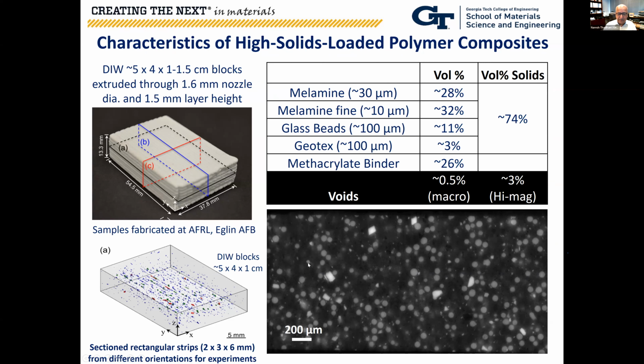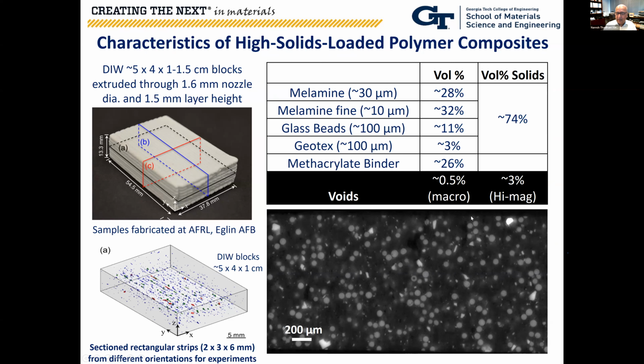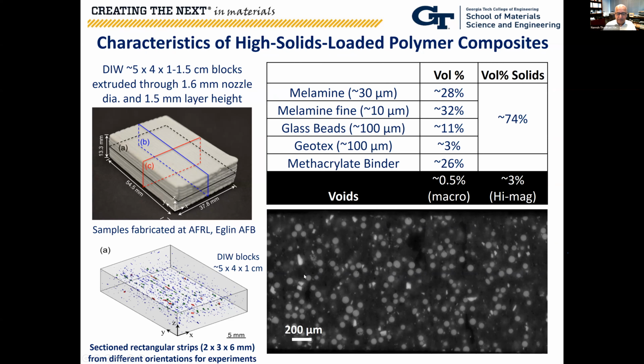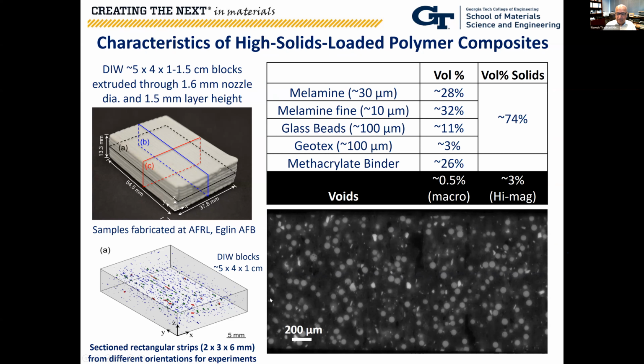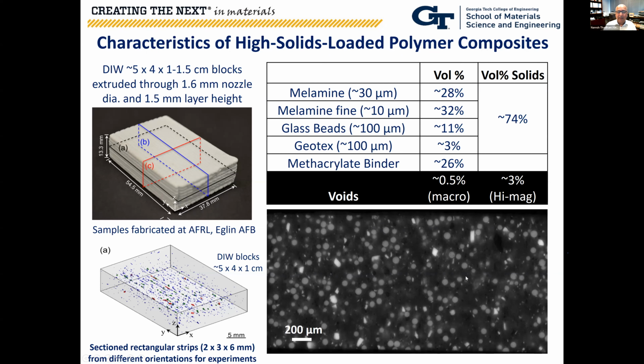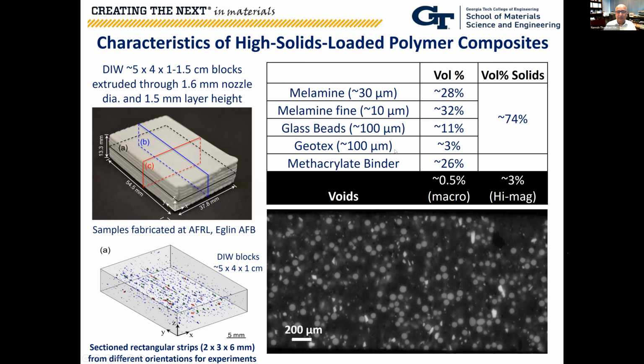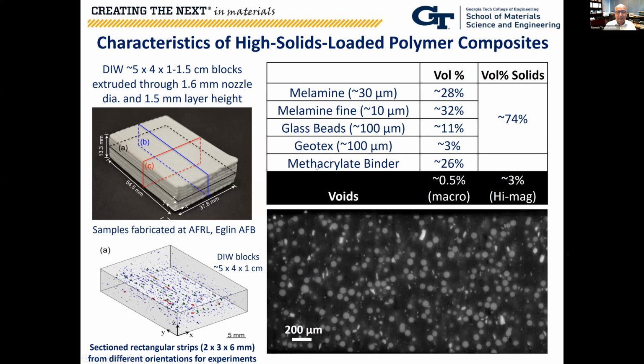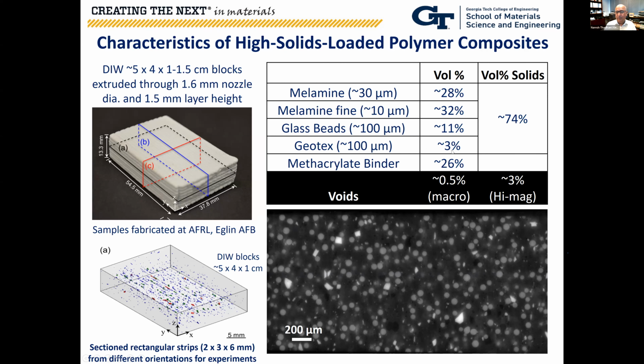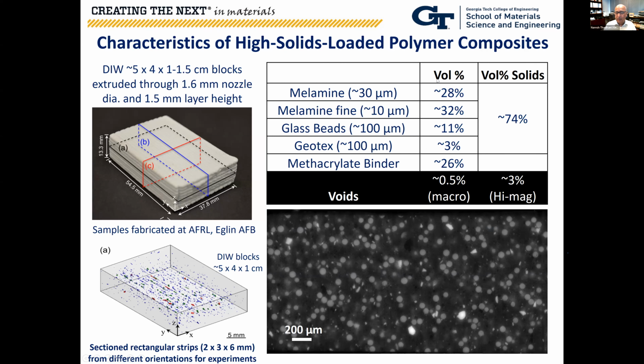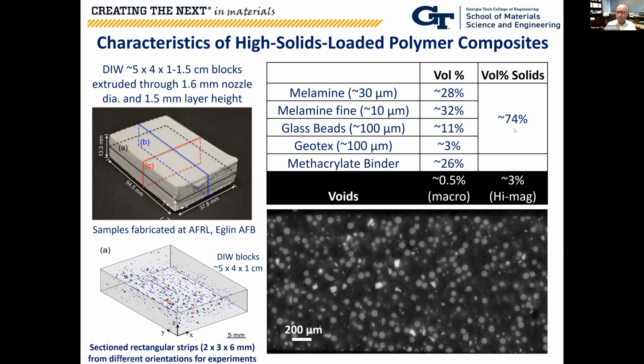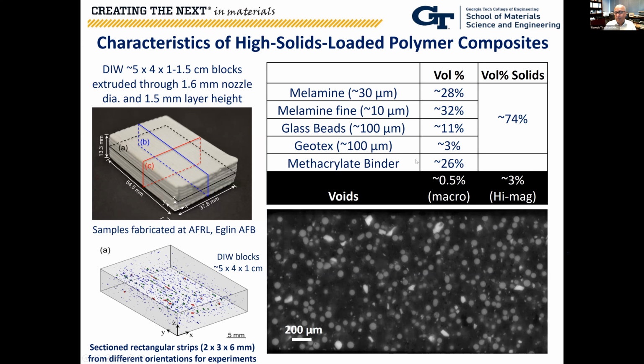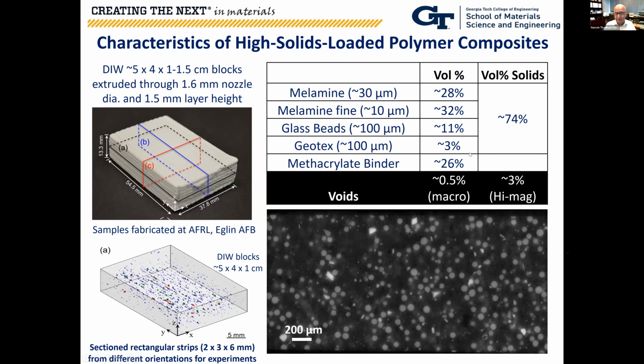And then geotex - these crystalline high contrast particles that you see coming in and out of the CT image - are about 100 micron size. The methacrylate binder is about 26%. So the total solid volume content is about 74%, and the polymer volume content is about 26%.